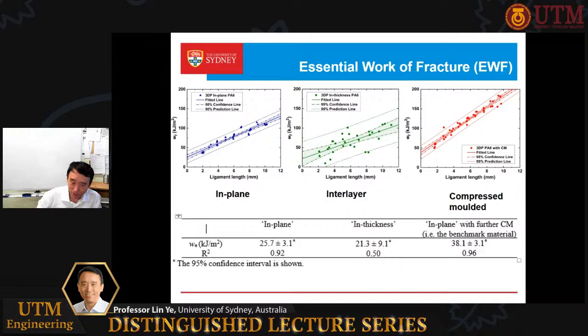You may ask, where does the defect come from? Even though we don't see a void there, there is no perfect molecular interdiffusion. When you're trying to fuse the particles or the filaments together, you have to allow the material between the two parts to interdiffuse across the interface. That takes time. So here it indicates either imperfect interdiffusion, or maybe some tiny defect.